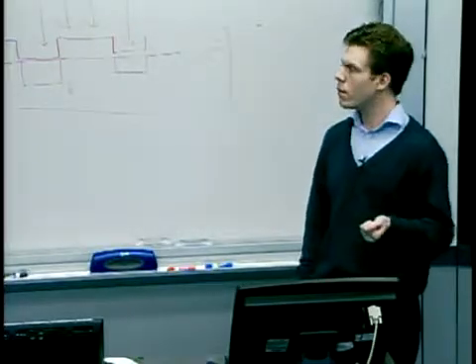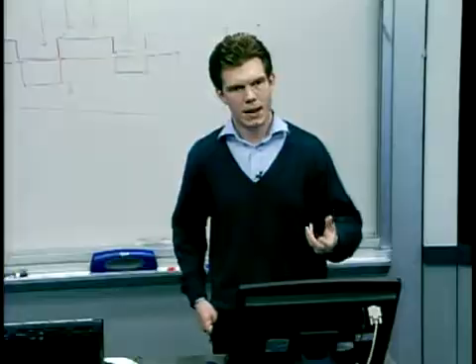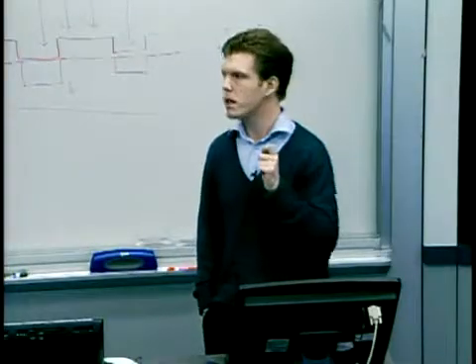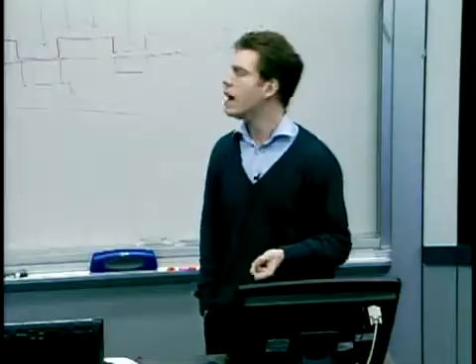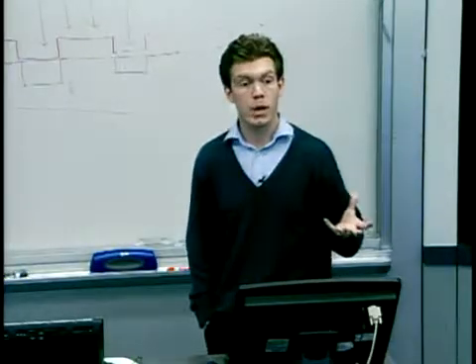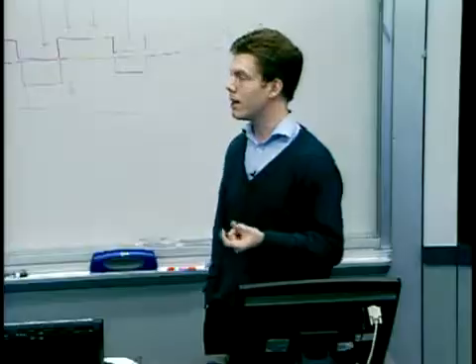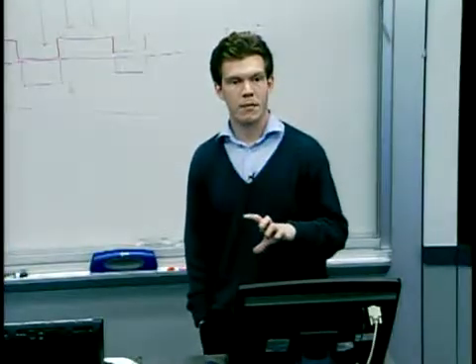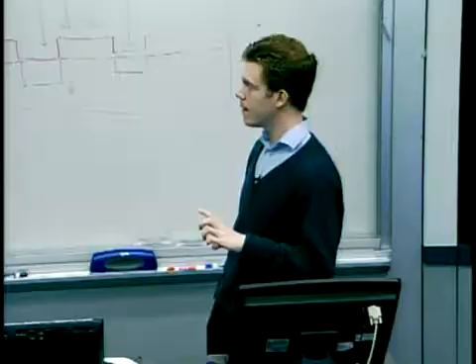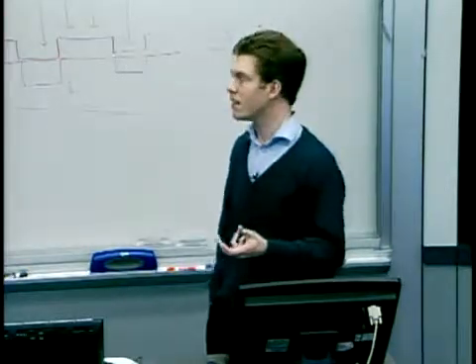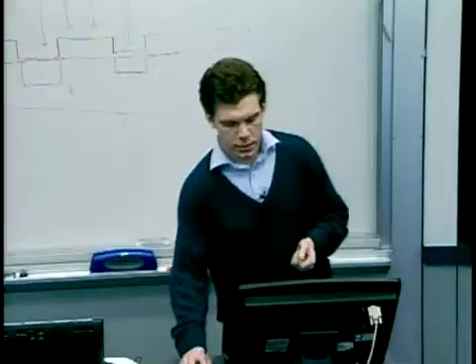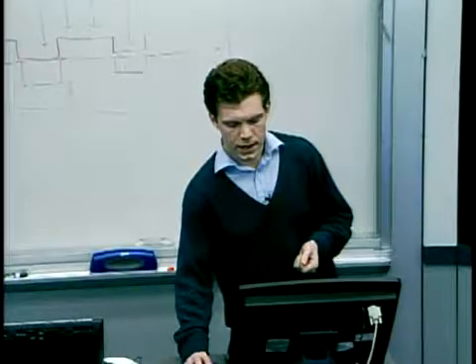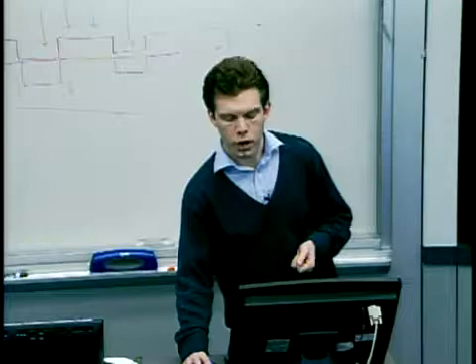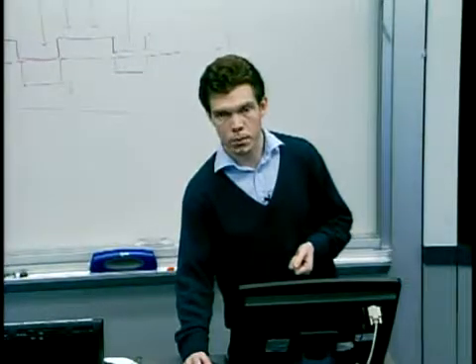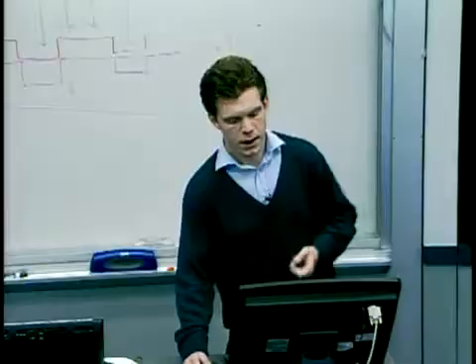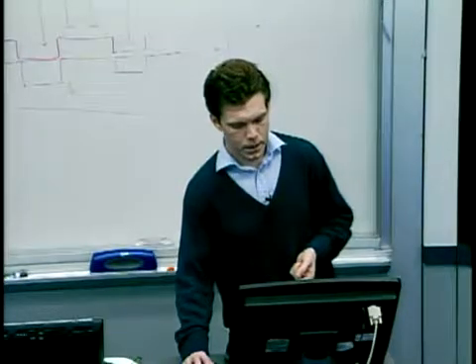The idea is that we want to describe how the surface of the material responds to a point load. If the material were linear elastic, and if it were substantially thicker than the dimensions of the features of interest, then the topography in response to a point load would effectively go as 1 over the radial distance from the point where the load is applied. And that's a standard contact mechanics result.